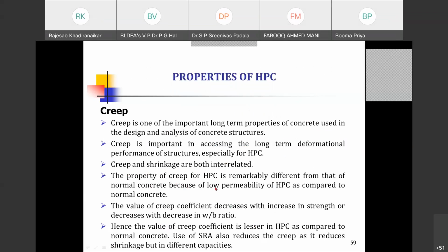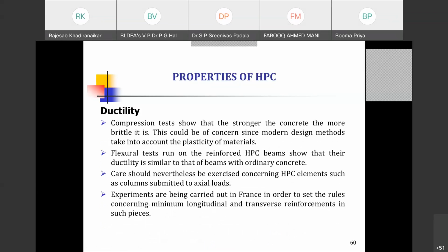The property of creep of HPC is remarkably different from that of normal concrete because of low permeability of HPC compared to normal concrete. The value of creep coefficient decreases with increase in the strength or decrease in the water binder ratio. And here we have a decreased water binder ratio and hence creep will be less. The value of creep coefficient is lesser in HPC as compared to the normal concrete. Use of these shrinkage reducing admixtures also reduces the creep. It reduces shrinkage also, but in different capacities.